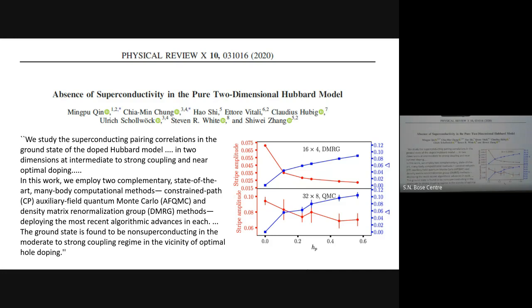What you want to see is that as you lower the external field, that creates pairing, whatever that is, the superconductivity has to win. And actually, in DMRG and QMC, in both cases, it loses. So that's just one set of results where these people compared the data by two different methods, and they said absence of superconductivity, and no one argues about this anymore.